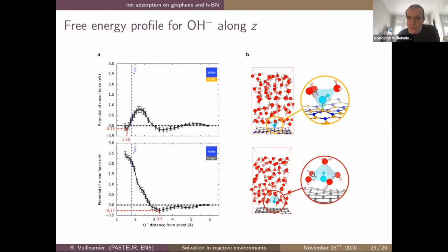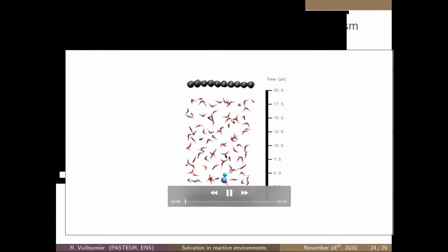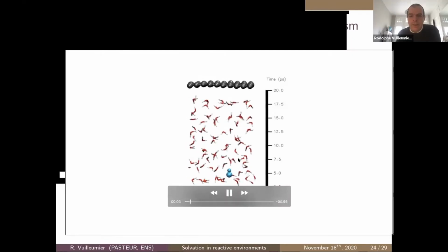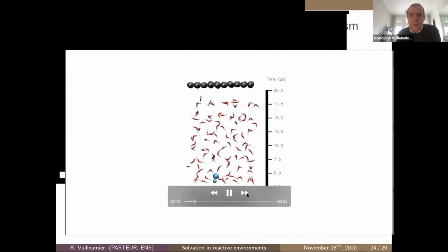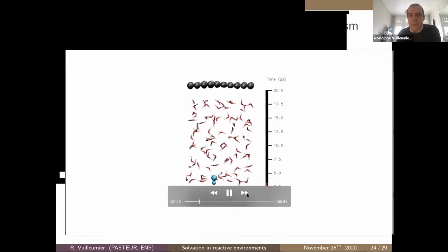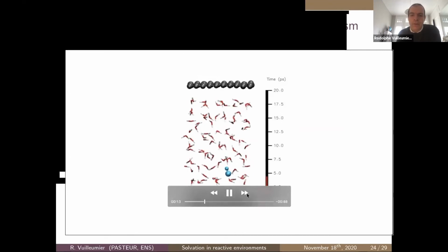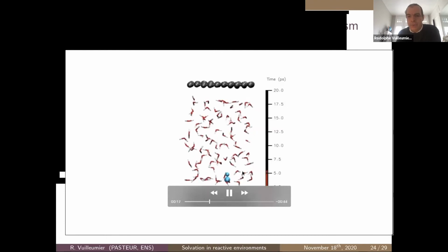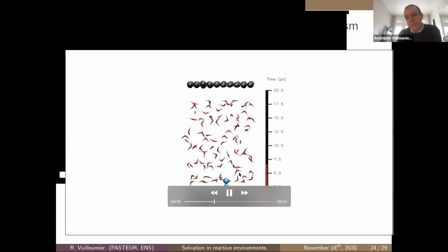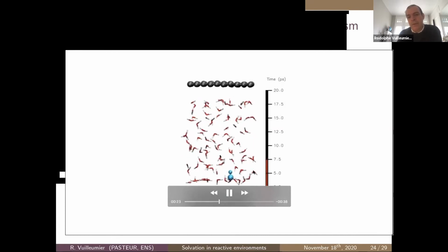And you see, in this type of simulation, it's really the way that the surface water molecules form hydrogen bonds, and the way OH minus is solvated in this region, that slightly favors the presence of hydroxide in this region. You can also look at the movie: if you have hydroxide in this region, it stays there for about 10 picoseconds in this movie. And we see that it's still hopping, because OH minus can have proton hops with H2O in the vicinity. But we don't have diffusion in the bulk. The OH minus is trapped in the surface region.